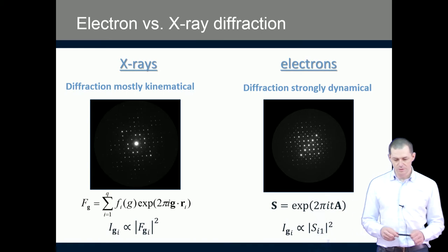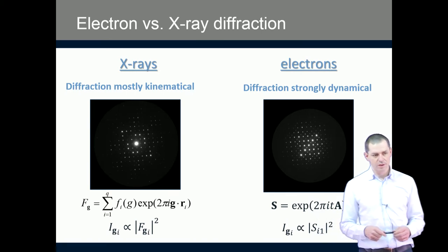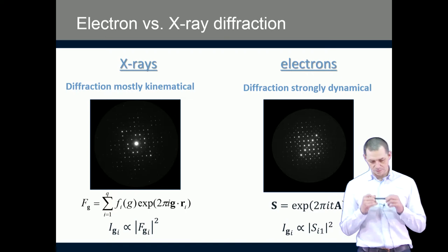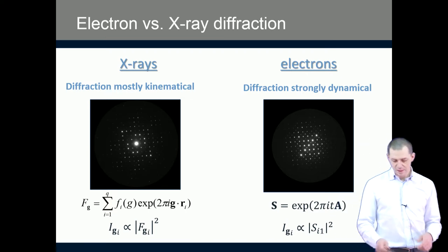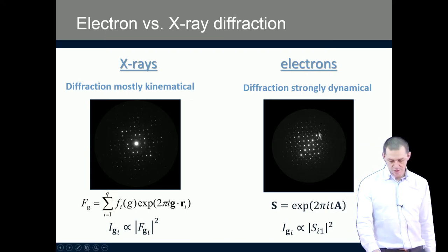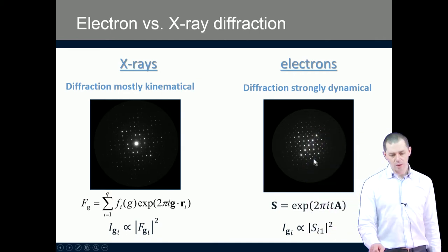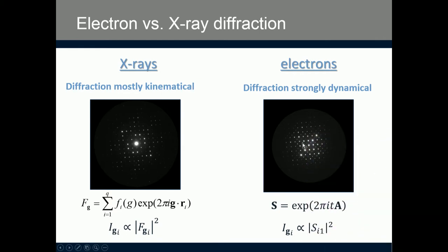The important consequence of this formula is that the intensities of each of these spots do not depend only on the structure factor related to that reflection, but on the structure factors related to all reflections that are in the diffraction condition at the same time. That makes analyzing electron diffraction complicated and also more computationally expensive and time-consuming.